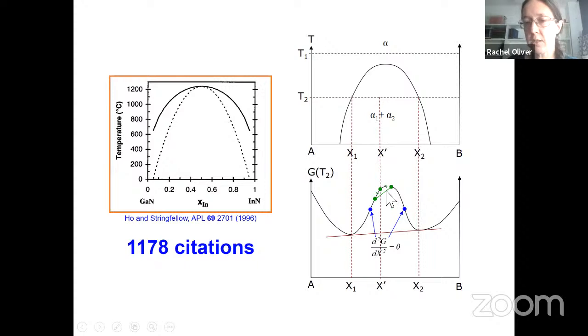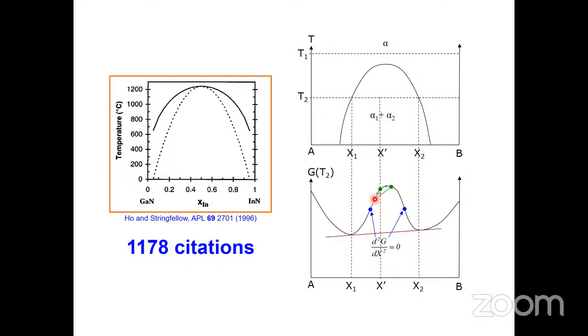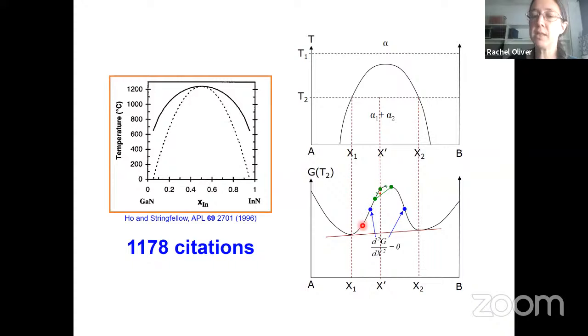And that's really easy to achieve here, because if we start off with material at composition X dashed, and just by a little random fluctuation, we see it have a slight change to being material which is slightly more B-rich on the one side and slightly more A-rich on the other. So we begin that process of splitting up the material, which was all one uniform phase, into this phase-separated version. Well, we have a bit of material at this energy, a bit of material at this energy on this side. So a bit of material at each of these compositions and these energies. And that immediately lowers the energy. So for compositions that are between these 2 points of inflection, as soon as the material starts to decompose into the high A and high B regions, then that will lower the energy. And that's an easy process because you're lowering energy immediately as you start to make it happen.